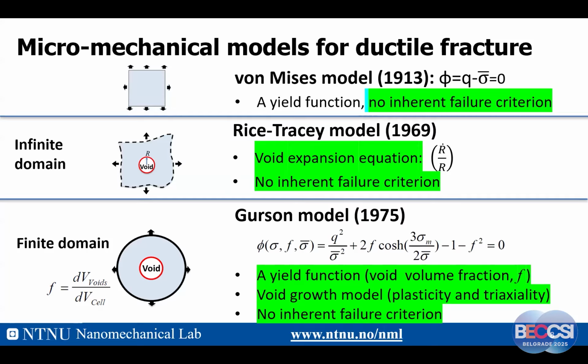Then let's look at the Rice-Tracey model. Here, Professor Rice again. It's a very famous model. If you think about it, we have an infinitely large plastic domain, and inside we have a very small void. Under plastic deformation and applied hydrostatic stress, we will have void expansion. So the Rice-Tracey model can calculate R dot over R. This is interesting, but there is no inherent failure criteria. That means you can probably use a critical value for this expansion, but you cannot predict the failure.